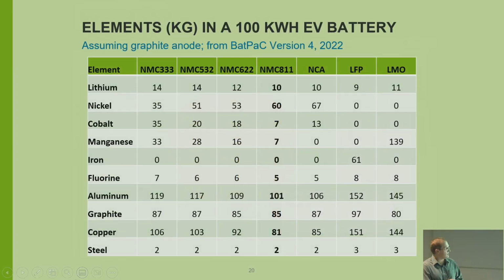So if we take some of those numbers, different materials, I'll try to speed up here, because we can figure out how much of every element is in a 100 kilowatt hour battery, which is kind of the new standard for EVs. So that's a vehicle that can do 400 miles. And you'll see that for the high nickel material, what we call 811, so that's 8 nickels, 1 manganese, 1 cobalt, that's how you read those numbers, we can see that that battery will have about 7 kilograms of cobalt, about 10 kilograms of lithium.